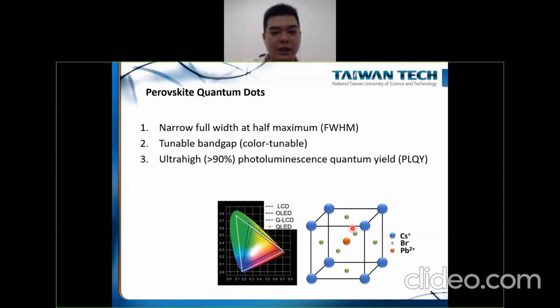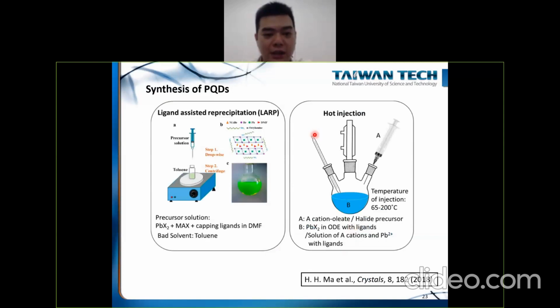And this is the synthesis procedure. The most popular procedure is called ligand-assisted reprecipitation. First you dissolve the precursor into the solvent, and then you mix them together and stir them on top of the hot plate, and then you put it into the anti-solvent. And you mix the precursor with the capping ligand. So when you inject it into the anti-solvent, the quantum dots will automatically form in the anti-solvent.